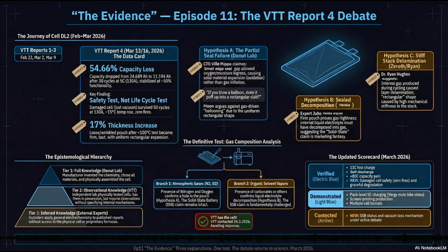Oh, so during the brutal 5C cycling, they were shoving ions into the maze so fast that they got jammed up? Exactly, like a massive traffic jam. The extreme current shoved the ions into the lattice far faster than they could evenly distribute. Okay. This trapped massive concentration gradients deep inside the rigid structure. The battery appeared dead because the surface was choked with ions, while the deeper layers were actually empty.